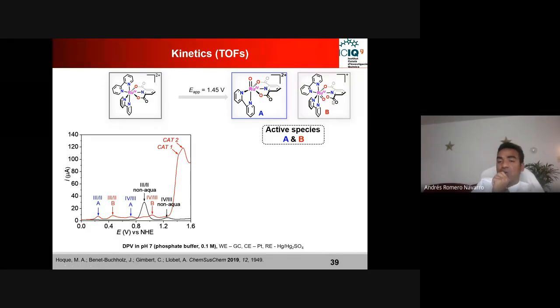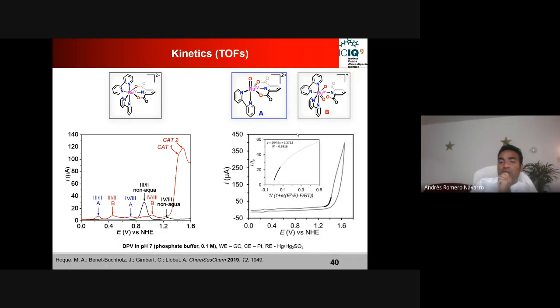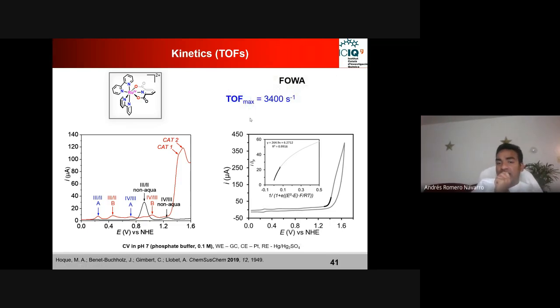So in that case, one of these carboxylates becomes decoordinated, and then the water molecule coordinates, and at high oxidation state, this water molecule forms this oxo compound actually. And then we measured the kinetics. So this is the CV, and we found that now the turnover frequency became 4 orders of magnitude higher than the previous compound I have shown. So this is a huge improvement in terms of the activity.